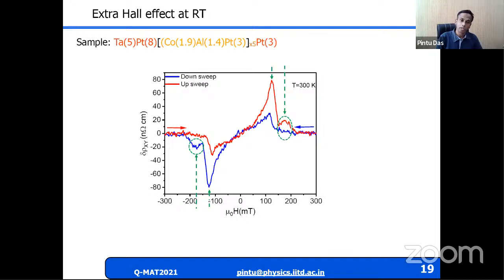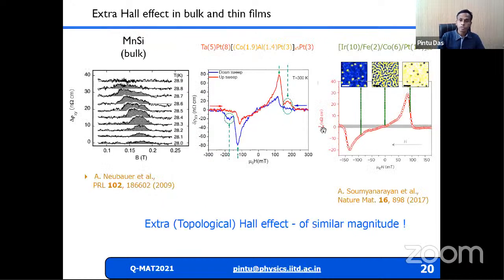The signal again here is in a similar range, of the order of nanoohm centimeter. We have measured it at room temperature. What we'd like you to notice is that in addition to these features, we are also seeing a shoulder-like behavior which has not been reported in literature yet. So this is just to show here that these numbers are in the similar regime.